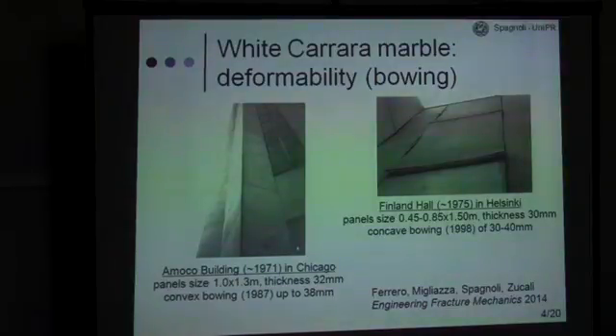The one on the left is the Amoco building in Chicago, where you can see that there are indications of bowing of the order of more than 30 millimeters in panels of the size of about 1 meter. And the one on the right is the Finlandia Hall in Helsinki, again with more or less the same size of bowing. And in both cases you can see the thickness of these panels is about 3 centimeters.